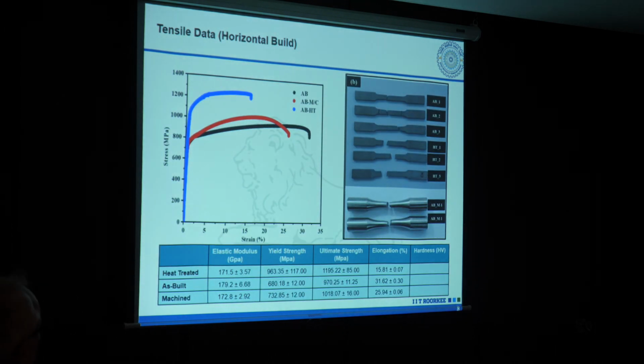Then we did the tensile analysis of the three material conditions. As built is the black curve, which has higher ductility and lower strength. As we did the heat treatment, the strength drastically improved at the expense of ductility, and the as machined condition is intermediate between the two.